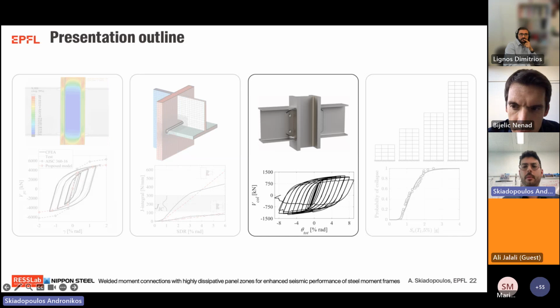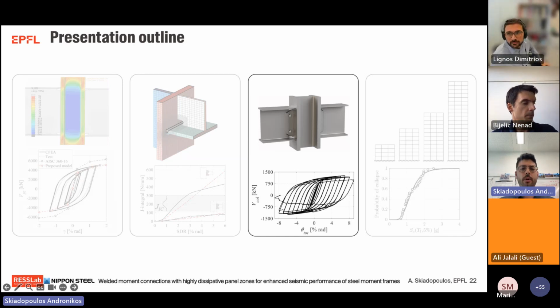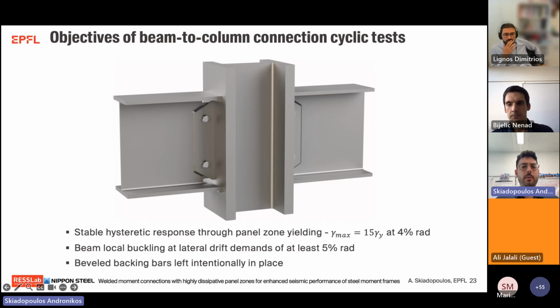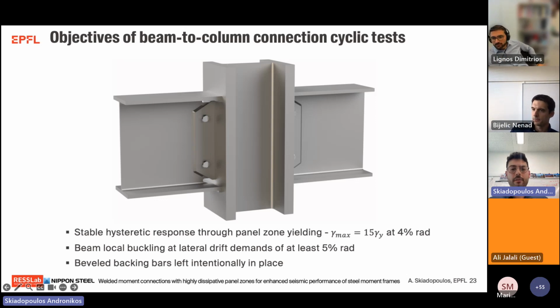To validate the proposed bevel backing bar configuration, we conducted full-scale beam to column connection experiments. And the primary objective of the experimental program was to enable the stable hysteretic response in the connection through panel zone shear yielding that was targeted to 15 times the shear distortion at yield at 4% story drift ratio, and therefore a delayed beam local buckling was expected to at least 5% lateral drift demands. A second objective of this testing program is to utilize the proposed bevel backing bar configuration I explained in the previous slide, and we kept it intentionally in place after the execution of the complete joint penetration welds in the beam flange to column face connection.